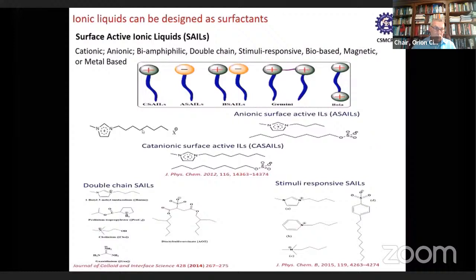Herein we have produced a single chain cationic surfactant by incorporating a hydrophobic group in the imidazolium group, and then anionic surface active ionic liquids have been synthesized by incorporating a long chain with the anionic head group, and then similarly we have made biamphiphilic kinds of ionic liquids by incorporating chains both in the cation as well as in the anion. And several other surface active ionic liquids like double chain surface active ionic liquids have been constructed. And then we also introduced stimuli responsive ionic liquids by taking a cationic part as well as delocalized pi electrons in the anionic part. So such kinds of ionic liquid surfactants have been produced by us.